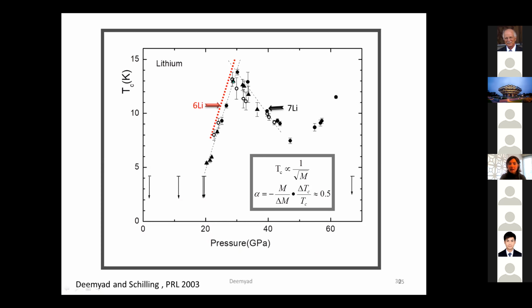And this is a curve that came from natural lithium, which is mostly lithium 7. Now, if we think about this as a simple metal, a BCS type of metal, then for lithium 6 we should, for example, see, with the dotted line, this isotope effect. And that's what we looked at.